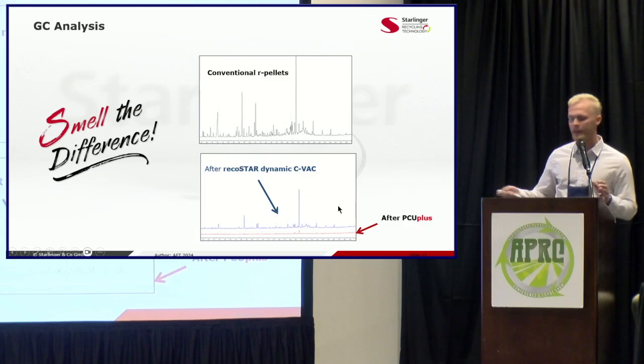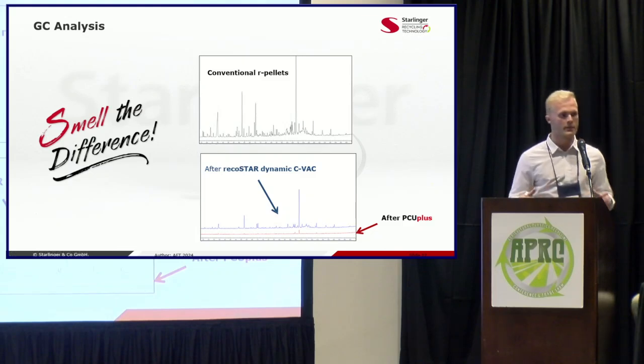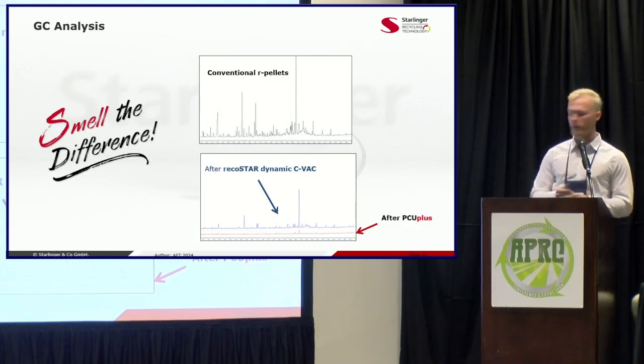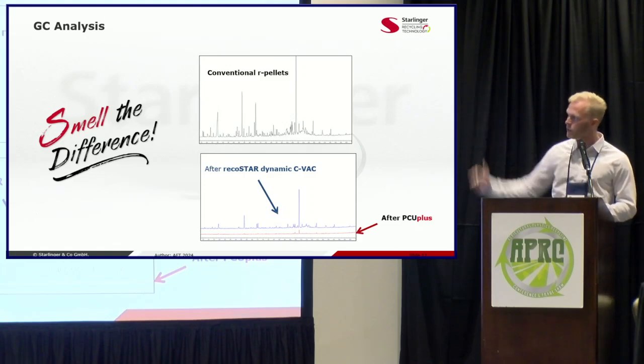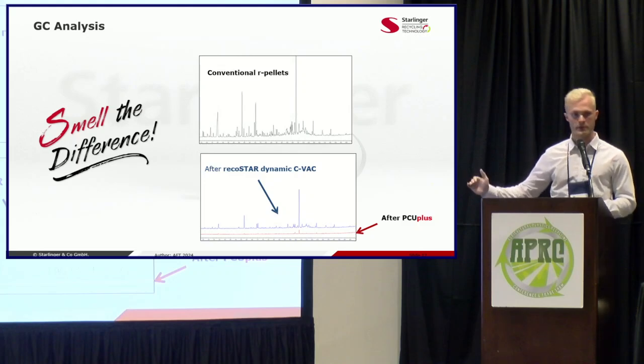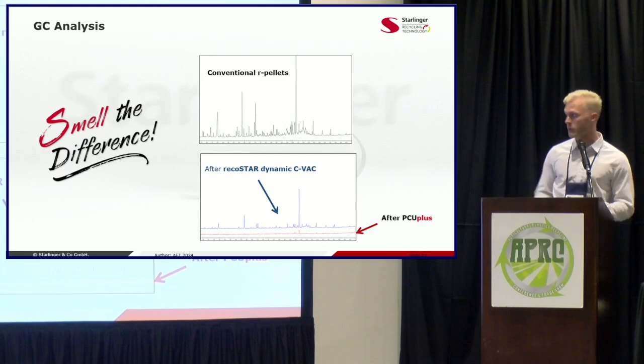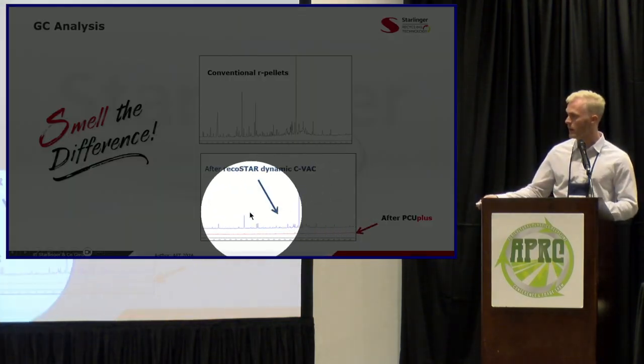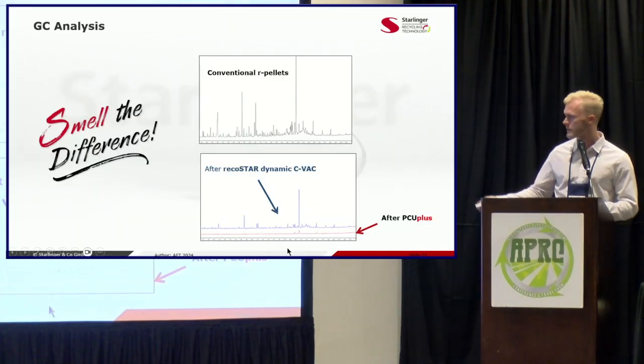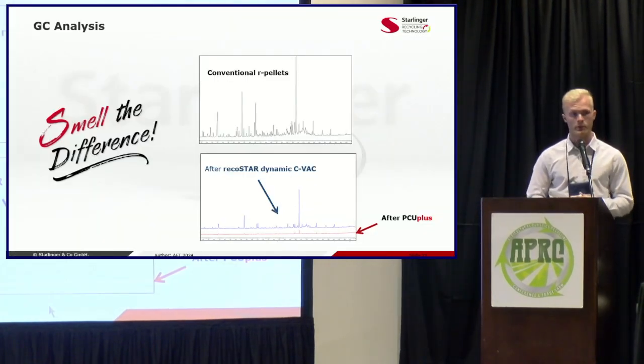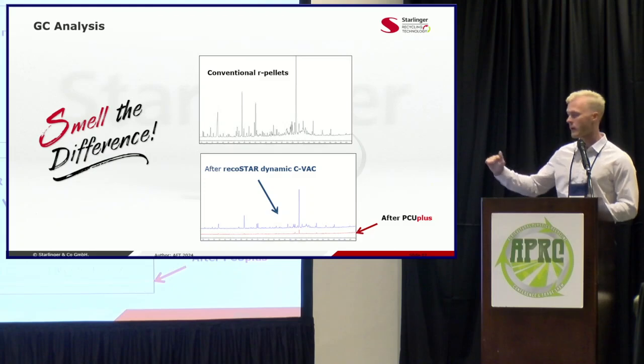Already, below here is this blue line, and that is that CVAC degassing unit that I mentioned. So this is when the pellet was pelletized right after CVAC, prior to treatment in the PCU+, and you can already see that huge reduction in VOCs, which is why I claim that we have the best degassing on the market, because it's really the most robust. And then afterwards, you can see down below, the red line here is the results after PCU+. So really almost a flat line.